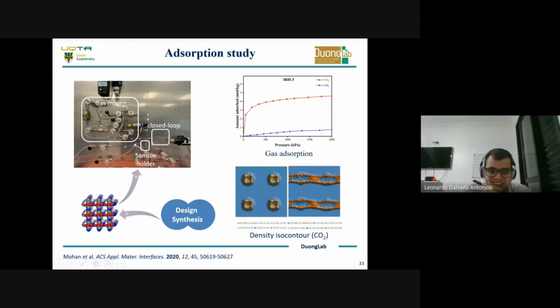What we did first was to study the single-component gases. In our case, we were interested in carbon dioxide and methane. For carbon dioxide, as you can see here, the uptake is less than 5, but the uptake of methane is not higher than 1. This adsorption study suggests that we might have a good material for gas separations, and this material is also capable of capturing CO2. So we can also use it to address some environmental problems related to carbon dioxide. Unfortunately, I will not have time to discuss that much, but I would like to invite you to look at this article that we just published recently.